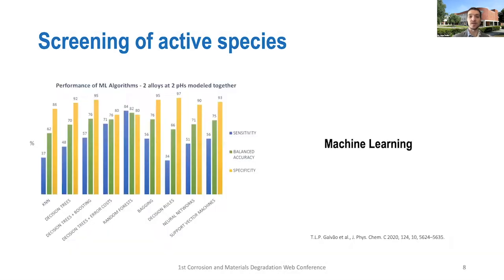Another possibility for the screening of active species is actually using machine learning models based on different chemical descriptors, properties, and conditions, and use them to select untested candidates before even going into the lab. The example I have here is from a recent work we published in which we tried to compare different machine learning models and to see which one would be the best to consider different conditions. Here, the conditions we were testing were data for 2 alloys and 2 pHs.